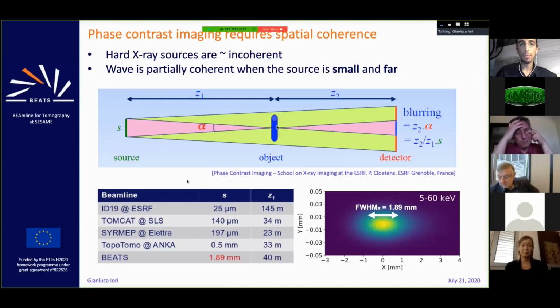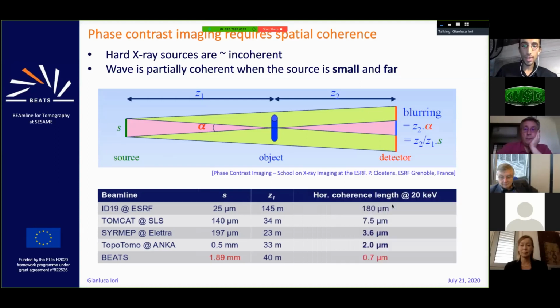The problem for BEATS, due to the parameters of the storage ring at SESAME, is with the source size. So when we compare the source size with other facilities, we have almost 2 millimeter full width half max source size, which represents a problem in terms of the coherence length of BEATS. So again, when we compare with facilities where we know phase contrast is possible, we don't reach enough coherence length for the application of phase contrast.